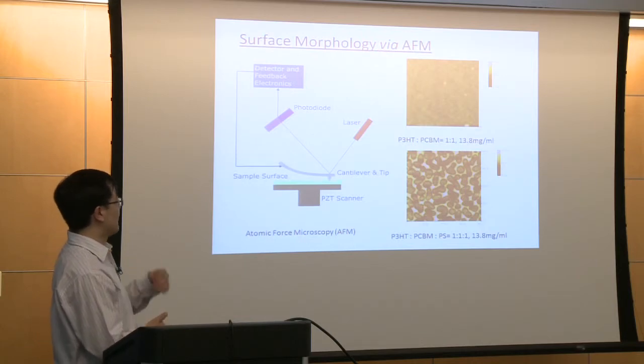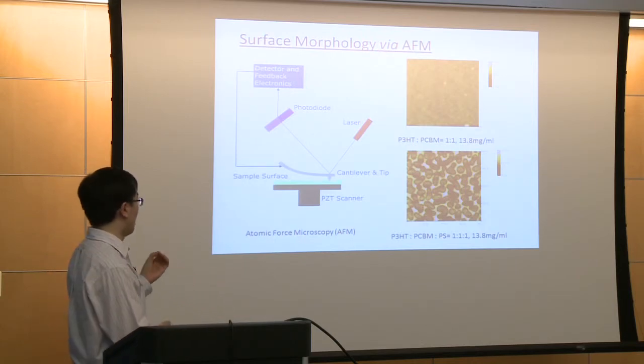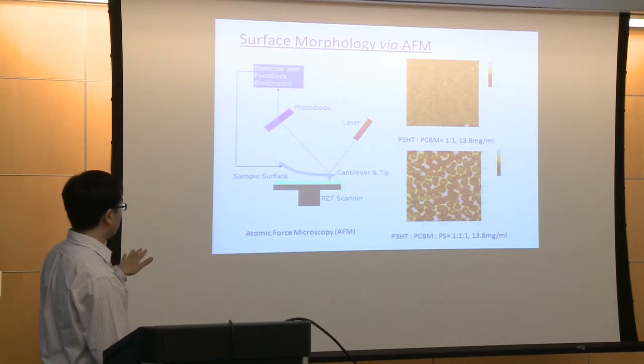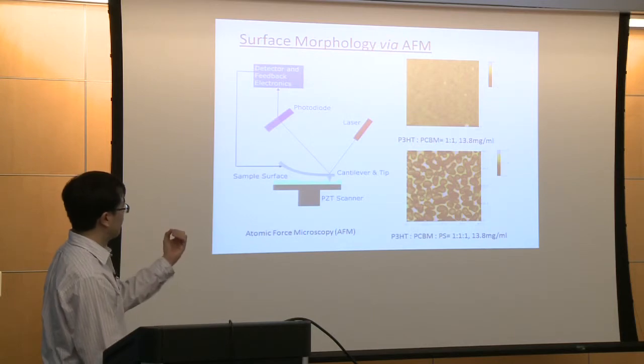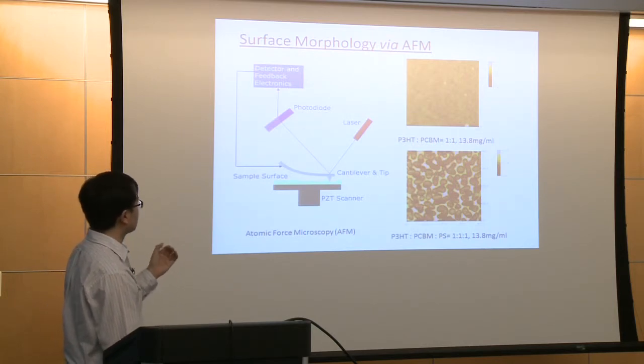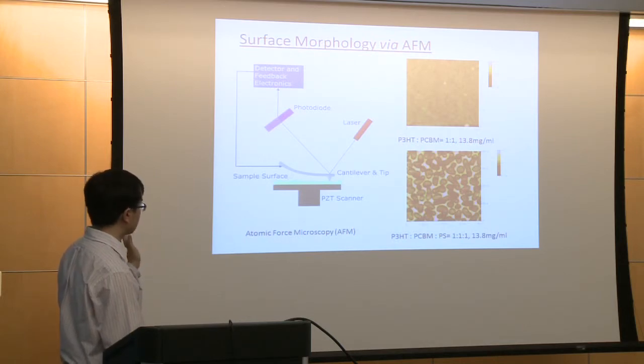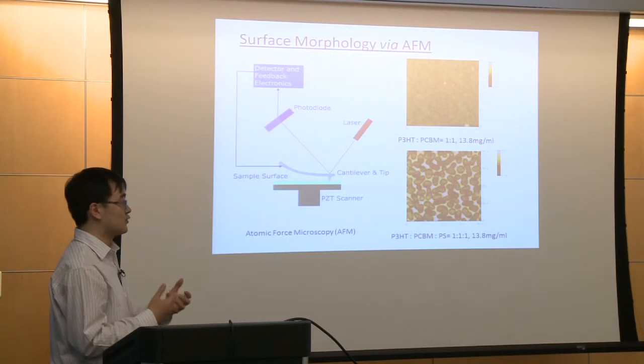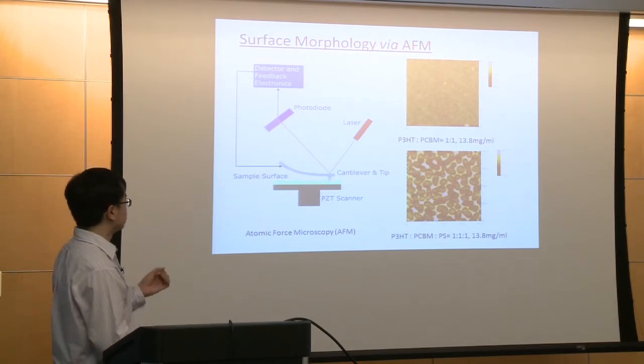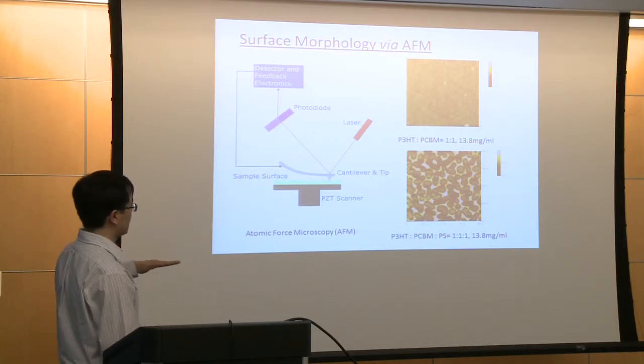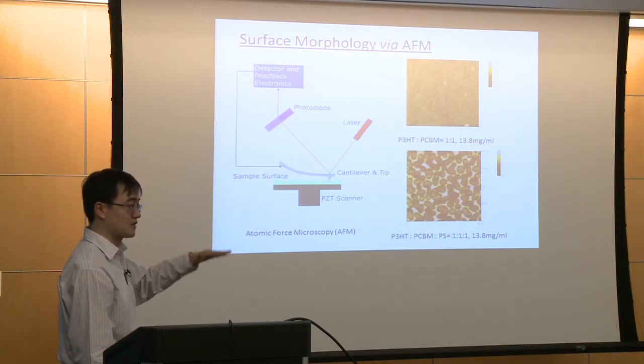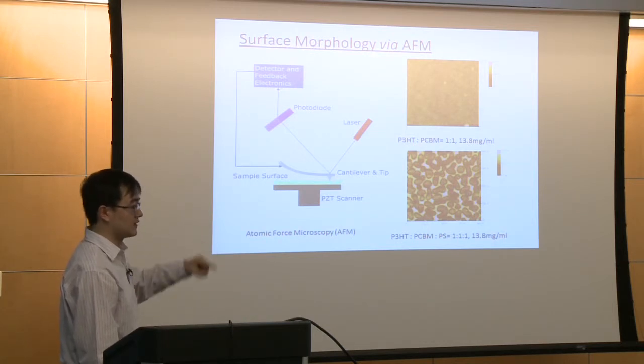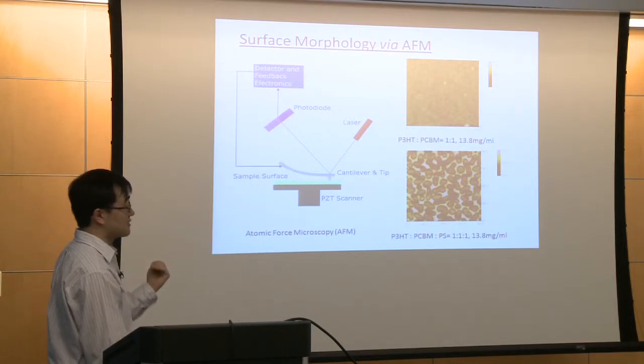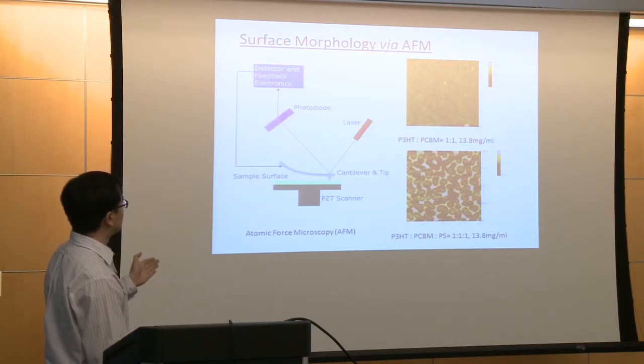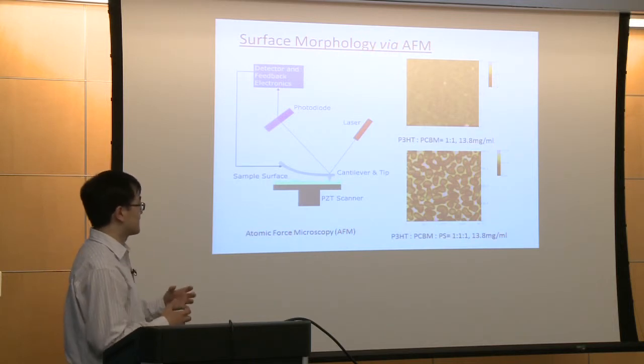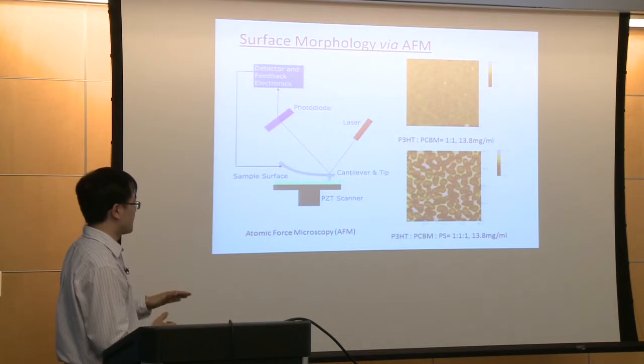And then we investigate the surface morphology by atomic force microscopy. The principle of the AFM is that the laser is reflected on top of the tip directly to the sensor, and the sensor transfers the electrical signal to the real image. When the tip is scanning along the surface, because there are different altitudes on the surface of the sample, the tip is deflected up and down. In this way, the electrical signal varies, and the detector and the feedback system give us the real surface morphology of our sample surface.